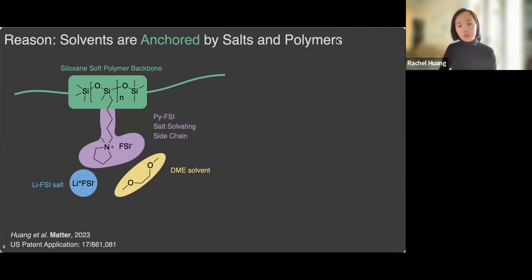Here I show the structure of our electrolytes. It has a siloxane polymer backbone. Those polymer backbones are silicone, which makes them quite thermally stable. We added PYFSI units. Those are like room temperature molten salt. They can solvate lithium salt. We added lithium FSI salt in the system. They're the main carrier of lithium ions in lithium-ion batteries.